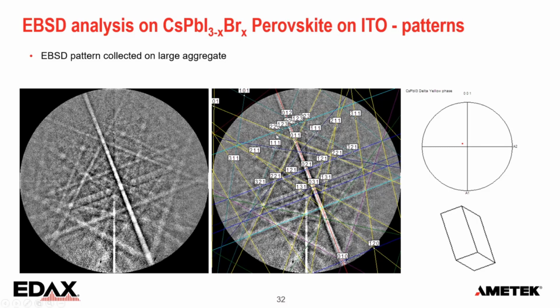So what you would need to do once you have a structure file like this from a CIF file, for example, you need to check if all the bands that are shown in the overlay are really present in the original material, in the underlying pattern. And all the bands that may have had a strong diffraction signal in XRD and are not visible here, we have to remove those. So we only use the bands that the software can pick up automatically.